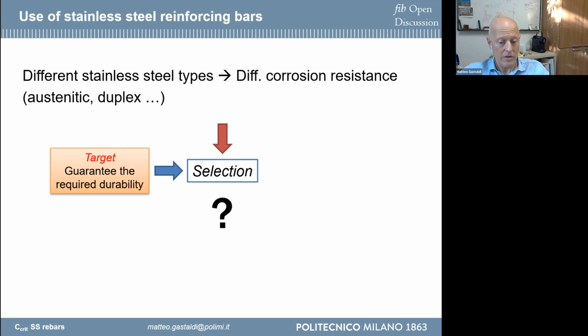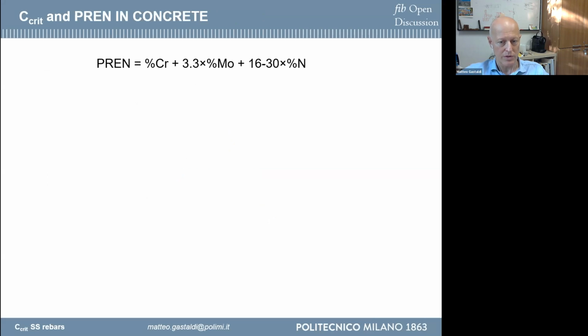And if you want to make a correct selection, it's fundamental to consider that we need to evaluate the critical chloride content for the different kinds of rebar. Generally, for applications that are not concrete, there is a number that is used to evaluate the corrosion resistance of the stainless steel rebar. This number is called the PREN number. This is the pitting resistance equivalent number.